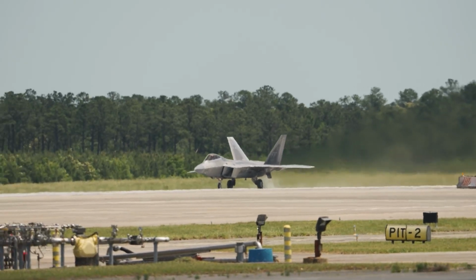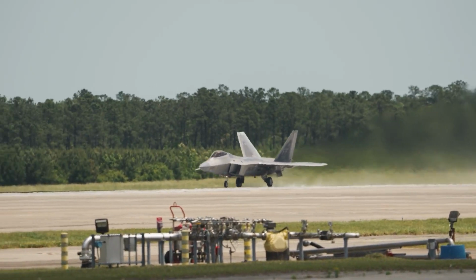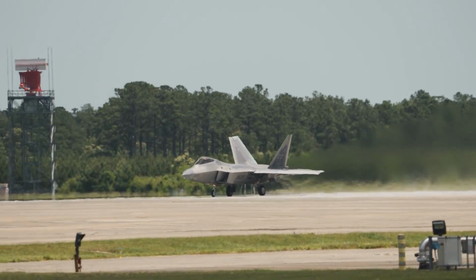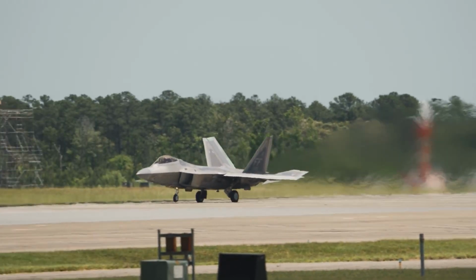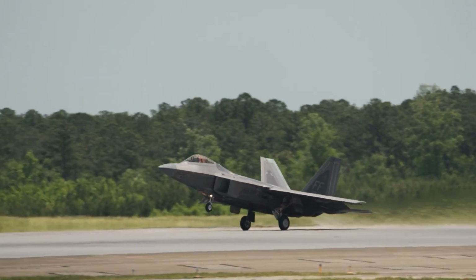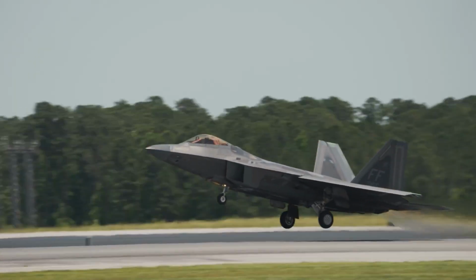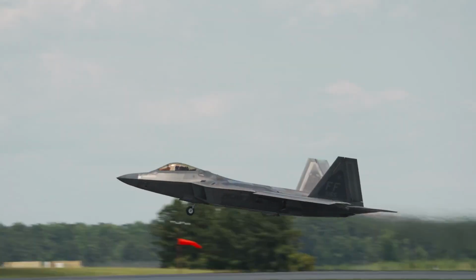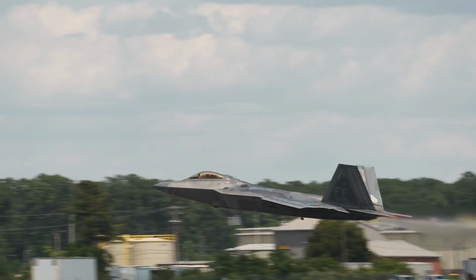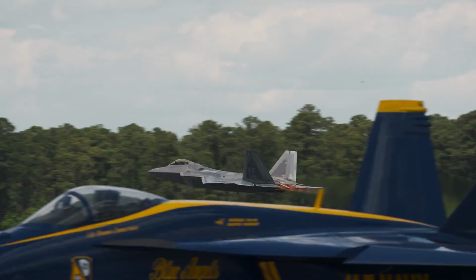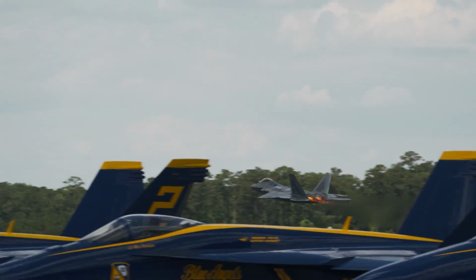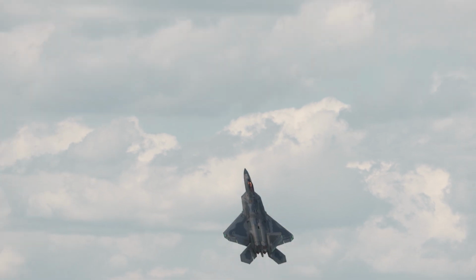And here's the thing. This coating is a nightmare to maintain. All this takes a lot of work to maintain, and many of these applications start degrading shortly after they are applied, with friction from high-speed flight, crushing G-forces, and the elements accelerating that process. Early coatings failed against rain and moisture when F-22s were initially posted to Guam in 2009.